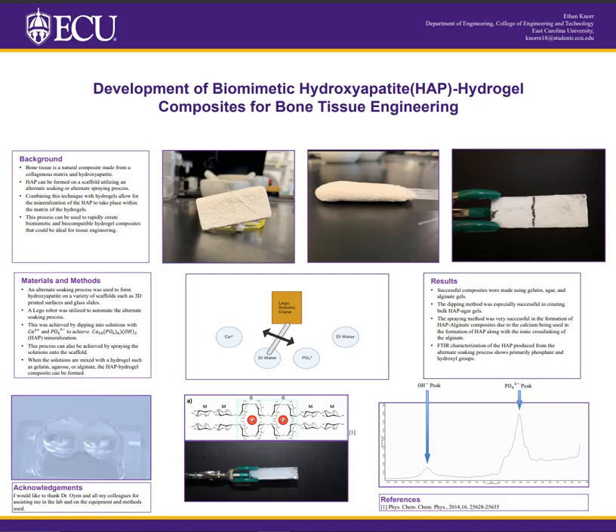Alginate gels differ from other hydrogels in that they are a polysaccharide chain that needs an ionic cross-linker to gelate. As you can see in the photo in the bottom middle, it shows the process of the calcium cation cross-linking the polysaccharide chain. Below that shows a freshly sprayed hydroxyapatite alginate sample after the cross-linking and mineralization has occurred.